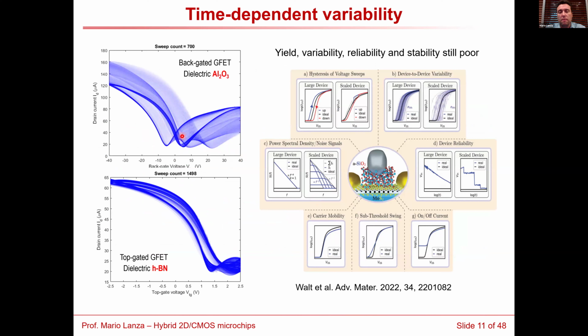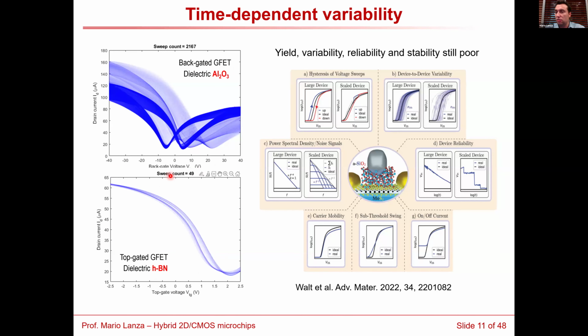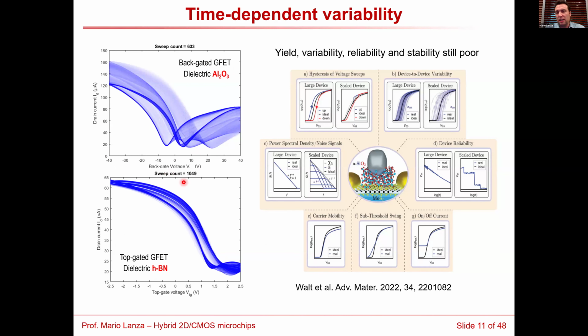And here you can see a couple of results when we measure thousands of IV curves in the same device. This is a backgated graphene field effect transistor with dielectric aluminum oxide. This is the same when we use boron nitride. It's a little bit better, but still there is some variability. And this has to be considered, and almost nobody studied this.